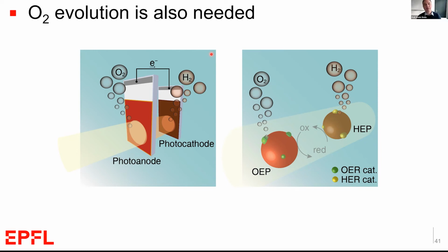I think the most significant challenge will actually be the stability. And there are a couple of aspects of stability that need to be addressed. The first is the actual link between the organic and the catalyst. Both the water reduction and the water oxidation reactions are catalytic. These require catalytic cycles and close active sites. The polymer or the organic semiconductors themselves, as far as I'm concerned, are not turning over the catalysis themselves. We're always going to have to add a separate catalytic site to drive the water reduction or water oxidation reaction. And that causes an issue because now there's a separate material that we need to get the charges to, and we need to make sure that that catalytic site stays at that interface.